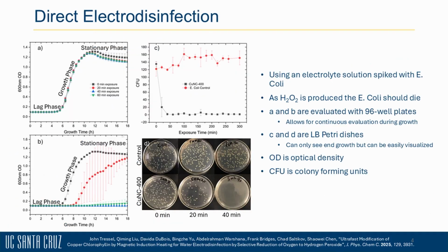To prove the direct water disinfection capabilities, we produced a neutral saltwater electrolyte that we spiked with E. coli, a common gram-negative bacteria found in the human gut and sewage. When we applied a current to our electrode setup, we were able to see significant bacterial inhibition after just 20 minutes and complete inhibition of bacterial growth after 40 minutes.